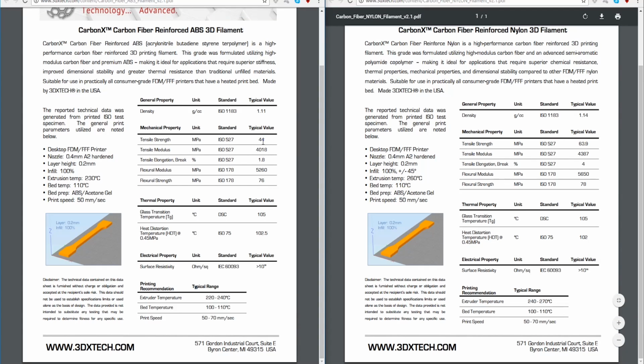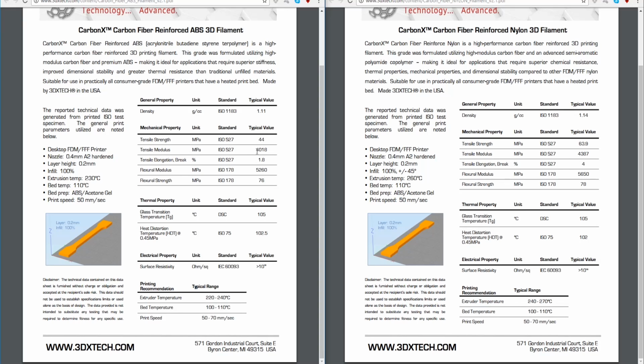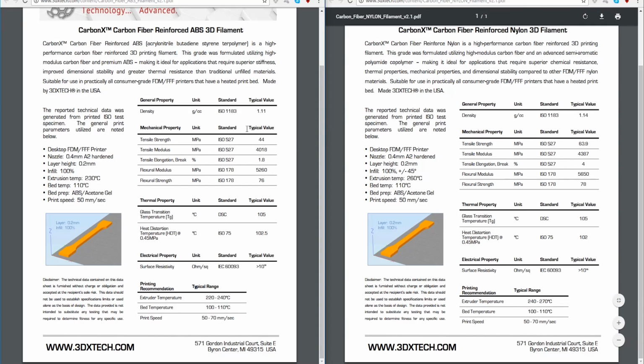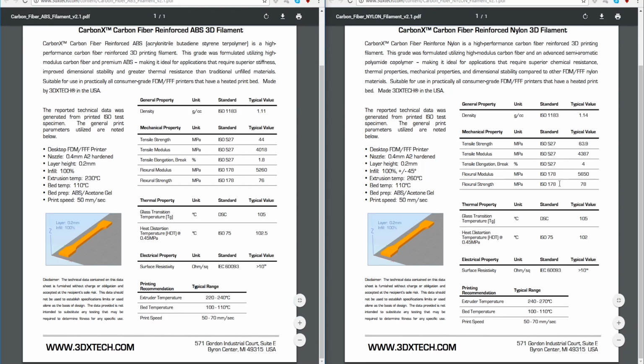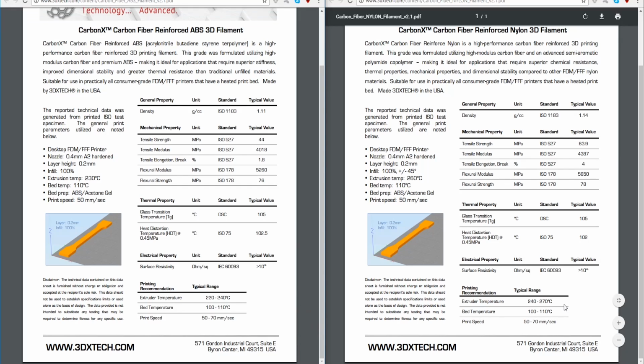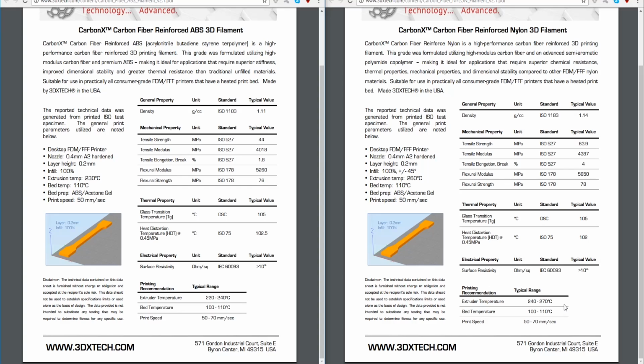So 63.9 to 44. Whoa. 41.8 to 5260, a little bit more dense by 0.03 grams per cubic centimeter. Better, better, better, just as good. Same, a little bit higher temp, a little bit higher temp. So, obviously, if you had the choice, you would pick the carbon fiber nylon over the carbon fiber ABS, because there's nowhere in the ABS that it beats the nylon, except for that you're going to need an all metal hot end to print that because of its higher temp.